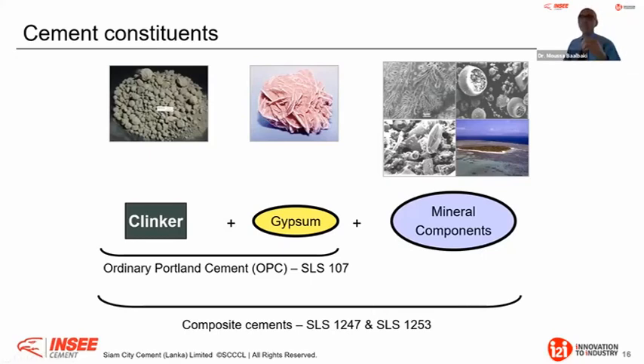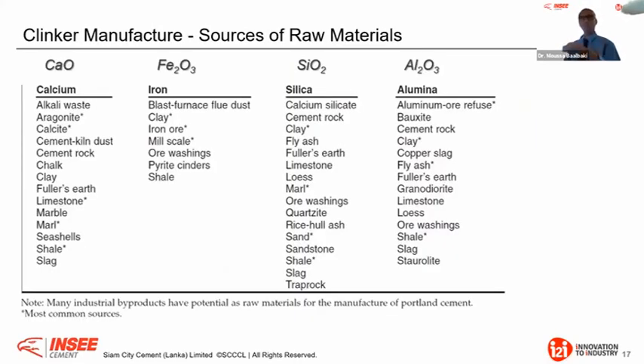Now, to go deeper on the clinker phase, we need raw material to produce clinker. As you know, in Sri Lanka we have only one facility to produce clinker, in Puttalam, owned by INSEE. For that, we need raw material. These are the oxides, like calcium, iron, silicon or aluminum, and here you have the most common sources. For calcium, we use limestone, we can use marl, we can use shale. The iron mainly comes from clay or iron ore, or mill scale in some places. Silicon will come from clay, marl or sand. And the aluminum will come from clay, mainly from shale, or sometimes from some byproduct.